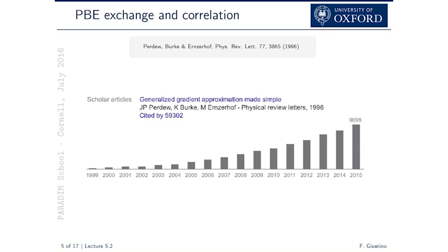The advantage, apart from the total energies, is that if you look at the equilibrium structures like bond lengths, it is pretty much similar to LDA. We see in LDA that we were underestimating lattice constants and bond lengths by maybe 1%, 2%. With PBE, things go the other way around. Maybe they overestimate by 1% or 2%, but we're still very close to experiment. So one improves the binding energies and the atomization energies, but does not sacrifice the structures. That's the reason why it is very popular.